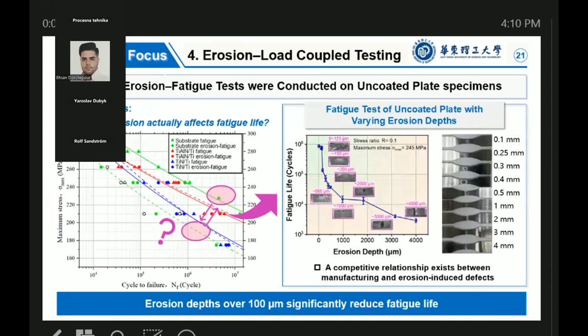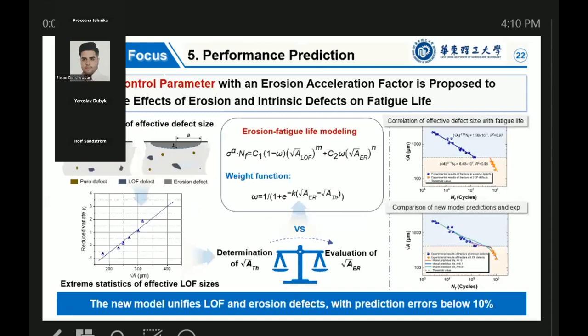And a key question is, how much does erosion actually affect the fatigue life? To answer this, we tested uncoated plates with controlled erosion depths. Results reveal a competition between manufacturing and erosion-induced defects. When the erosion depth exceeded 100 micrometers, fatigue life dropped sharply. Below that, the effect was minimal. To capture this behavior, we proposed a life control parameter, including an erosion acceleration factor, used as a weighting function to dynamically switch between dominant defect types, highlighting the critical defect size in fatigue life control. This unified model achieved a prediction error below 10%, demonstrating it is both accurate and general.